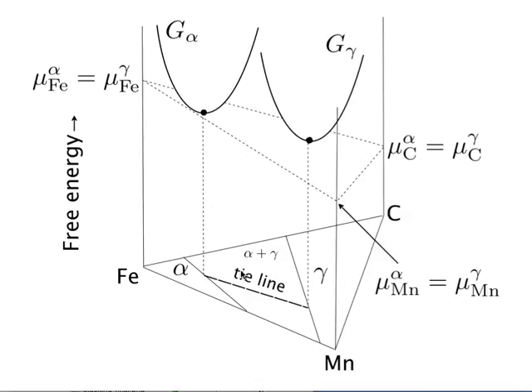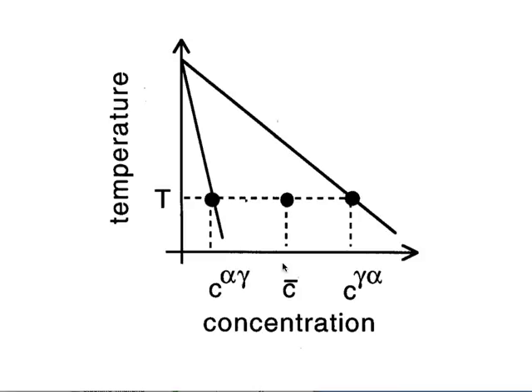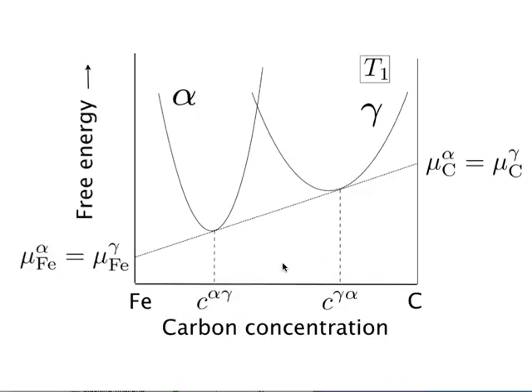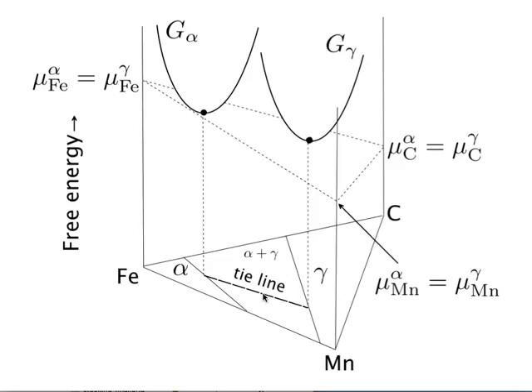So, we've got to actually grow something. Which tie line would I pick controlling the process? The obvious answer is the one passing through C bar, through the average composition of the steel, as in the binary case. So here, you see, the tie line actually passes through C bar. And similarly, we would have two values of C bar for carbon and manganese. And when we plot that on our ternary phase diagram, we ought to pick the tie line that's passing through C bar. Makes sense, doesn't it?